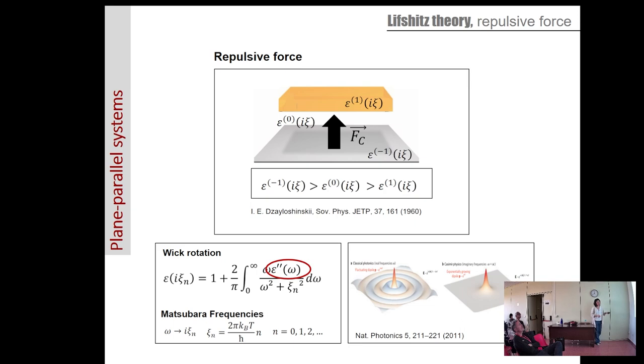Another thing to check is that these frequencies are the so-called Matsubara frequencies, in which we are going to rotate from the real axis to the complex plane, just by doing this Wick rotation, where we are going to integrate over an infinite range of frequencies the losses of our material. So we can see already another problem, which is that we don't always know the refractive index or the permittivity of the materials in an infinite spectral range of wavelengths.